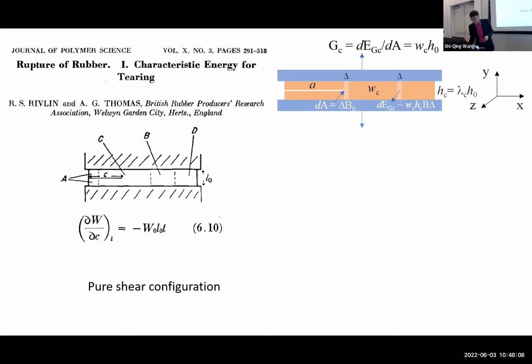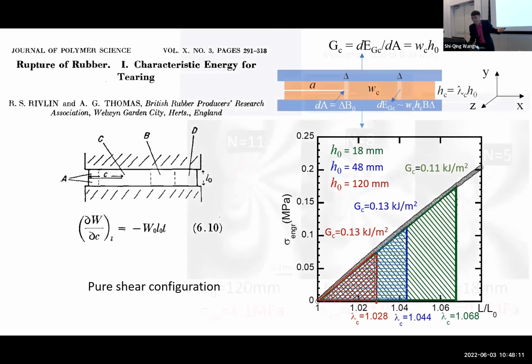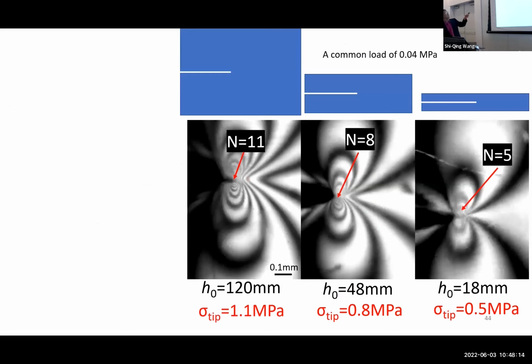What happens on the next slide? So basically this is what happens. You prepare a sample that's taller versus shorter, okay? And what was said was that the taller one will break much earlier because we have so much more volume to store the energy, right? Okay, and I was so mad with this argument. But look at what happened. At the same load, the taller one simply has much more intensified stress at the tip. You follow me, you guys?